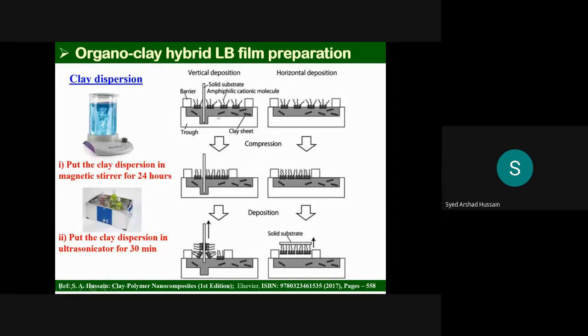Clay material lies in the subphase. When it comes close to this floating material, they attach through a cation exchange reaction or electrostatic interactions. Then we compress the barrier, and depending on the organization we want, we transfer the film onto the solid support. This is one process. And another process is we gently take the substrate close to the material, it touches, then the material attaches to the substrate and we take it out. Then we study. But it depends on the property of your substrate and of course your material.